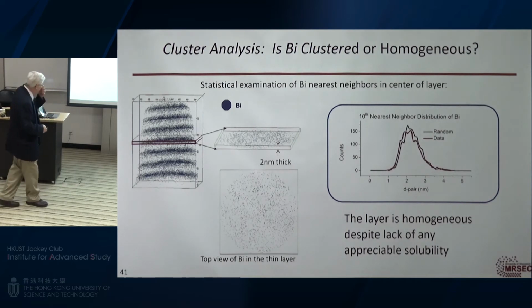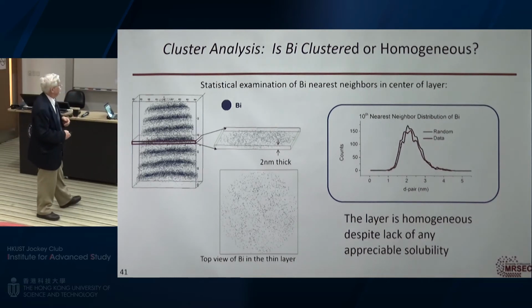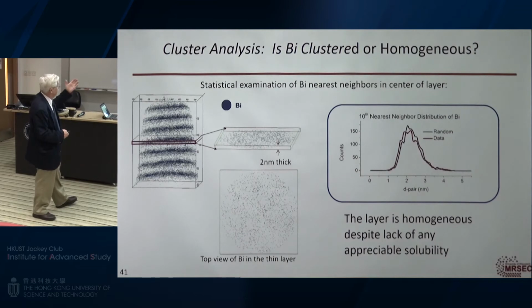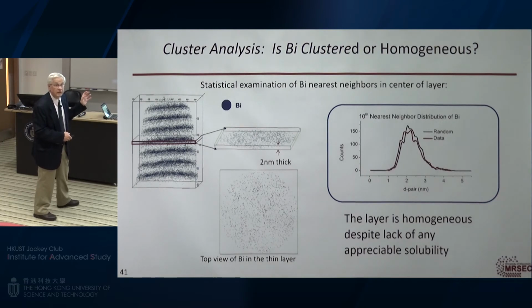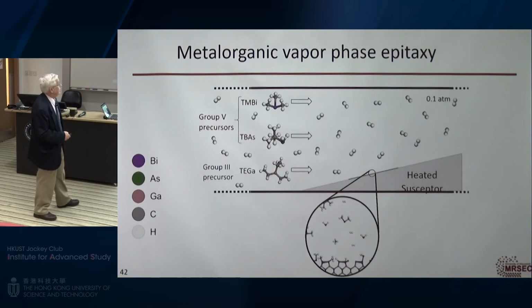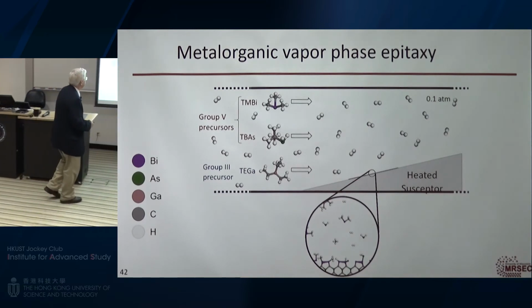So why does this happen? Why can we get so much bismuth in this material? It's metastable. If I heat that way up to 700 degrees for a little while, all the bismuth will form droplets because it doesn't want to be in solution. And so let's look at this in a little more detail.